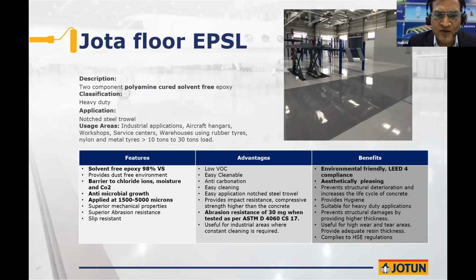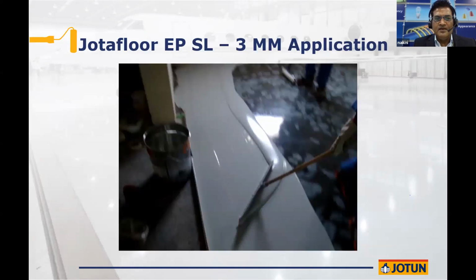So we have a very unique product here. It's solvent free with nearly 100% solids, barrier to chlorides and moisture, antimicrobial growth, and applied up to between 1.5 millimeter to 5 millimeter. And it has an abrasion resistance of only 30 milligrams per 1,000 cycles when it's measured under the CS17 category of abrasion resistance, ASTM D 4060 standard. This is a video of how it's applied.